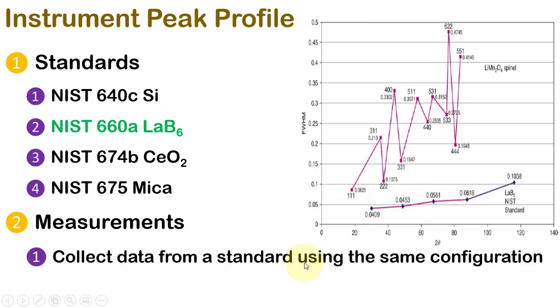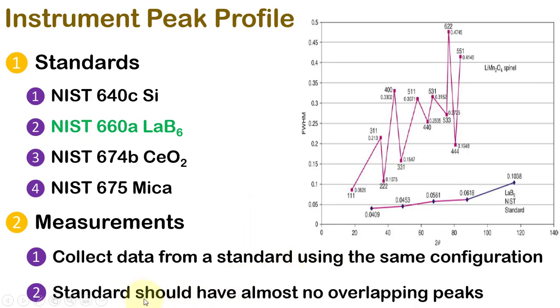In the measurement, we will have to collect data from a standard using the same configuration as adopted for the sample. And there should be almost no overlapping peaks of the standard with the sample.